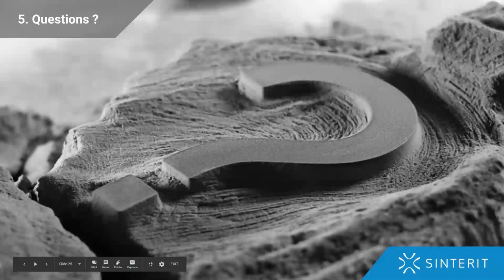Okay, next question. If you print an assembled model at a specific angle, is it true you can use a smaller gap? That's a tricky question. Can you use smaller gaps? I would say no. I would say it's like as follows. Let's say you have two rounded objects, a cylinder and a cylinder, a ring basically. So a cylinder and a ring. If you place them perpendicular to the plate, the build plate, the gaps, let's say, should be 0.2 or 0.3 millimeters. If you do it at a certain angle, probably the gaps would have to be more than 0.2 or 0.3 millimeters. Why?